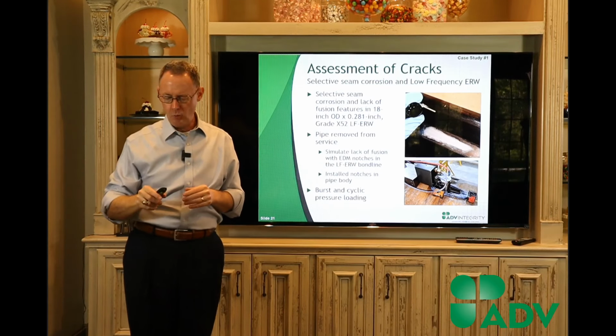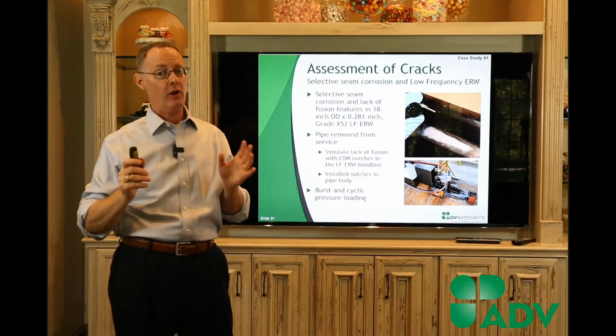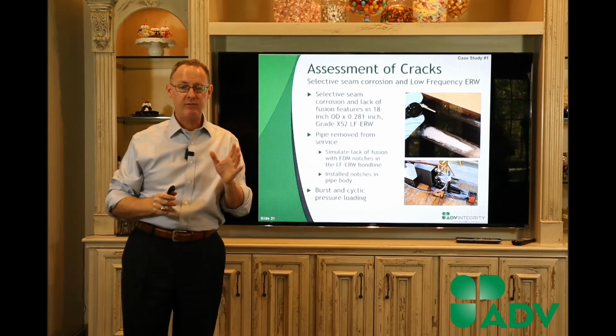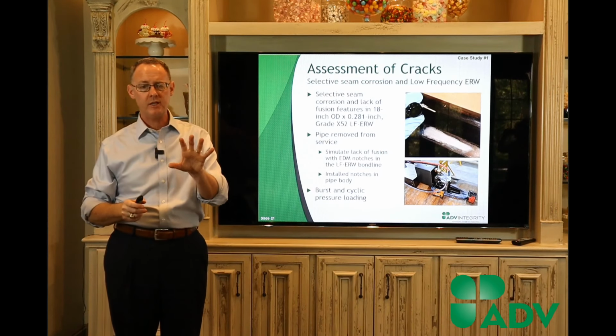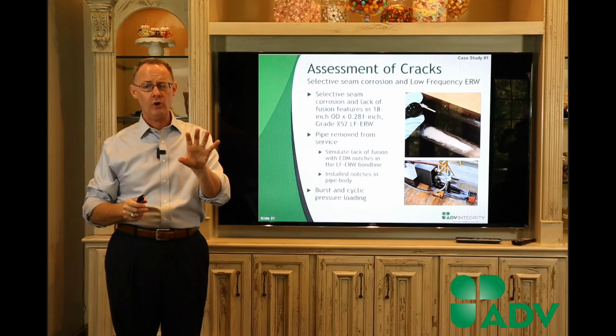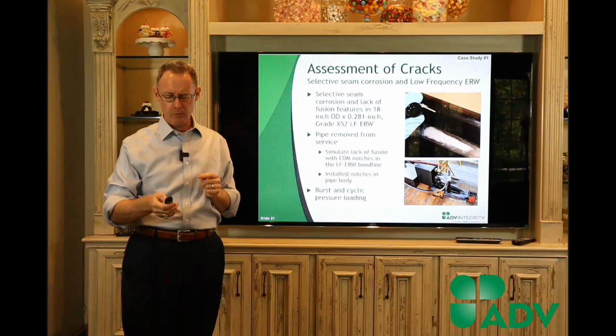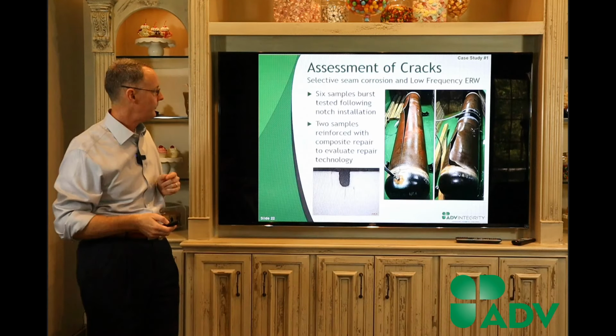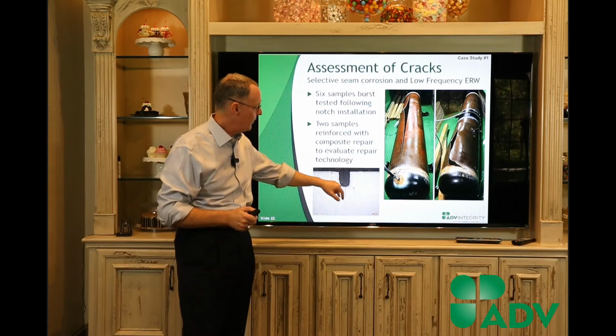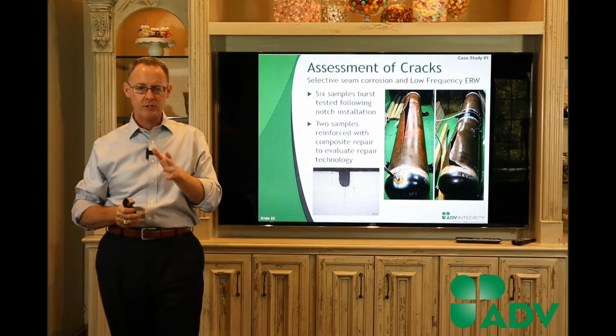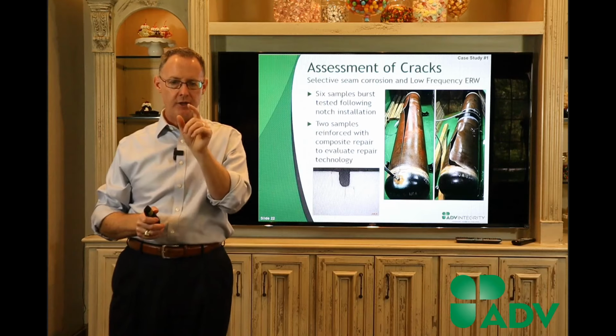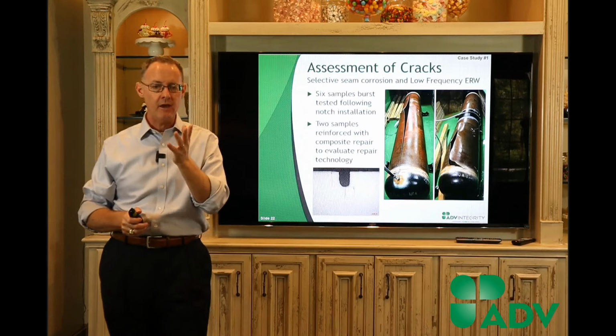So we are mechanical engineers. We're learning a lot about metallurgy, and it's very important as we go through that process that we make sure that we've got that information before we start putting notches in pipe. And these are just some tests. So what you can see here on the bottom left is there was a crack, and we cycled it to create a crack at the base of that notch.